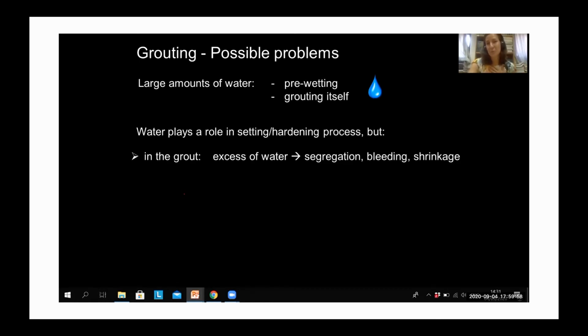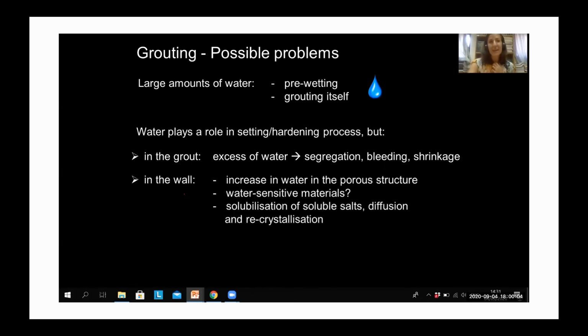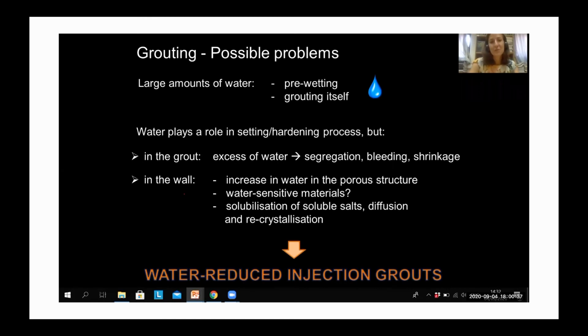But an excess of water may lead to segregation, bleeding, and shrinkage of the grout. And also in the wall, what can happen? For sure, there is an increase in water in the porous structure, and then it's very difficult for the water to leave, to completely evaporate. It's a problem if there are water-sensitive materials. And in case of soluble salts, that will lead to their solubilization, diffusion, and recrystallization, with all the mechanical damage which this can entail.